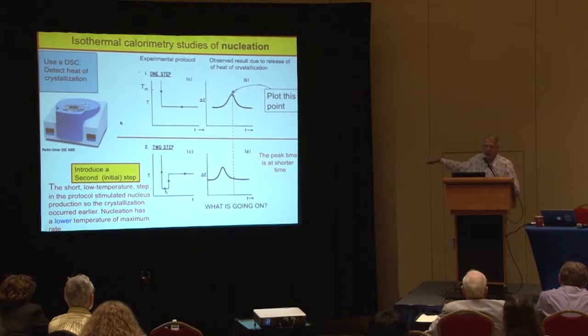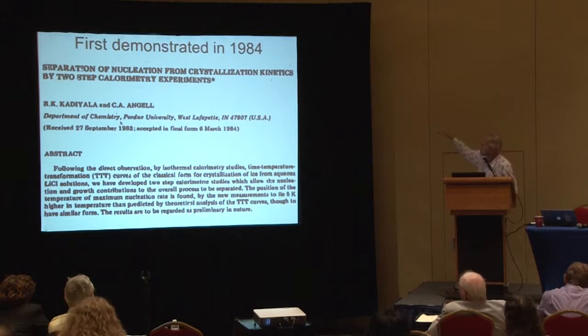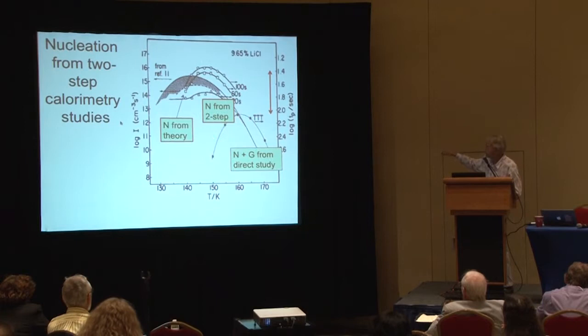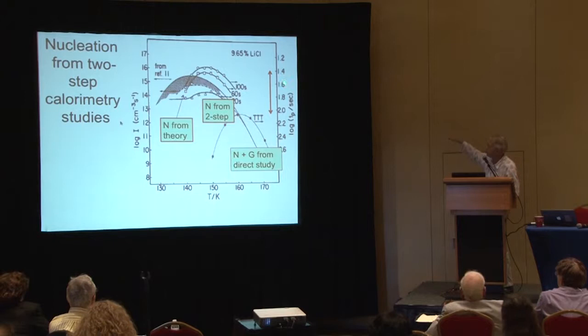And this was the first paper, I think, a 1984 paper describing this. And here were the results. This was the TTT curve from the one-step method. This was the deduced nucleation rate from the McFarlane paper. And here was the experimental one. And this is the difference in time scales, which is not quite an order of magnitude, but it tells us that we would have to cool at least five times faster to bypass the nose of the nucleation TTT than we did to bypass the nose of the nucleation plus growth TTT curve.